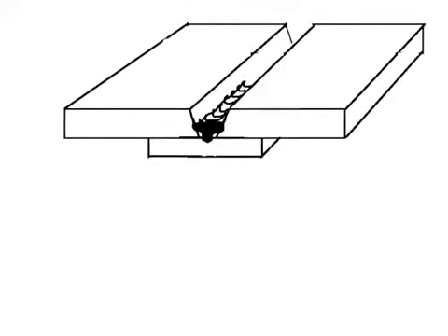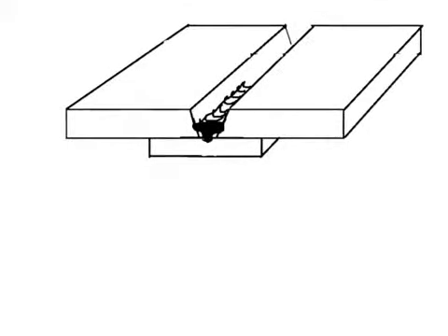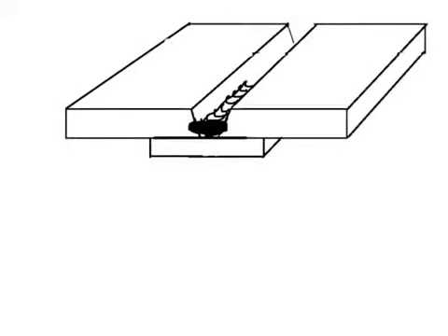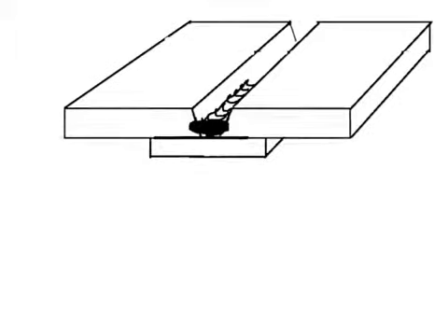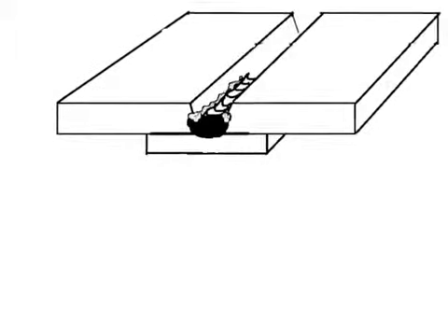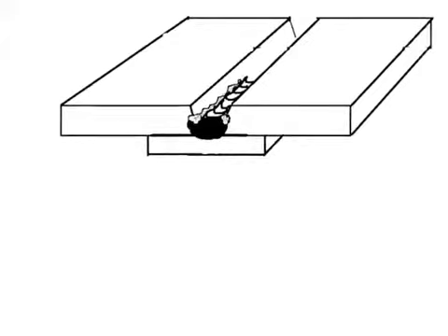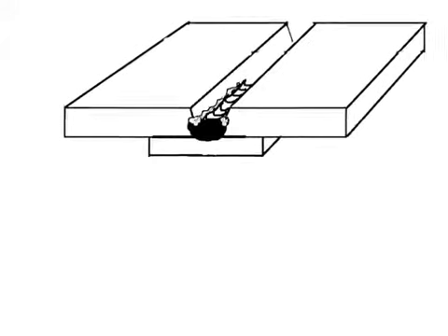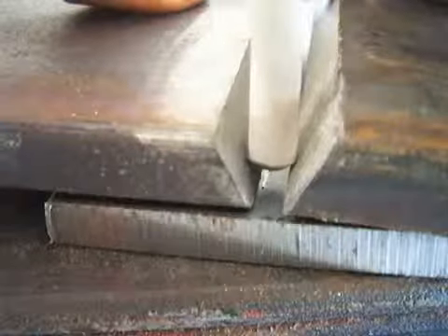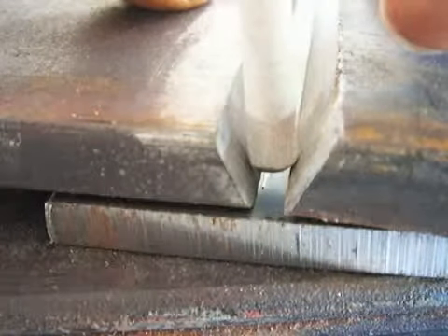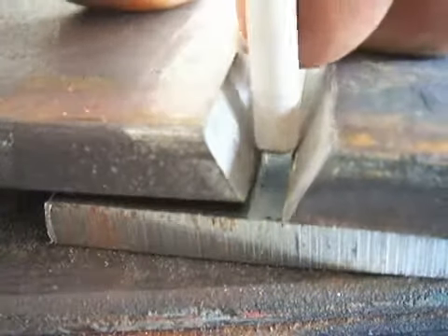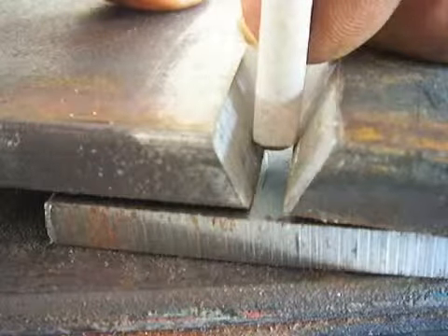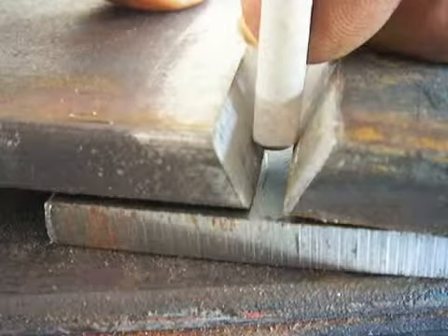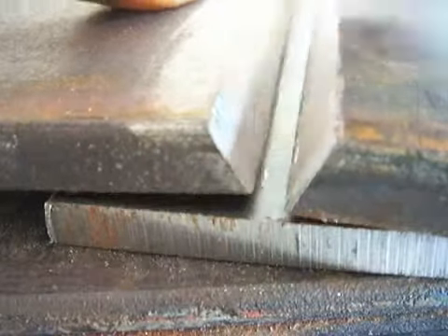You don't want to penetrate into the walls and to the backing strap but leave voids on either side, either lack of penetration or slag inclusions, and you don't want to penetrate deep into the sides but leave slag inclusions against the backing strap either, and you don't want to dig undercut on each side that can't be burnt out with the next pass. So again, gap it wide enough, which means about a 1/4 inch. You can see if you don't gap it wide enough how far the tip of that rod is away from the backing plate. It's just really hard to burn in that deep.